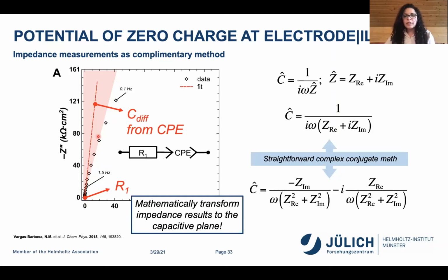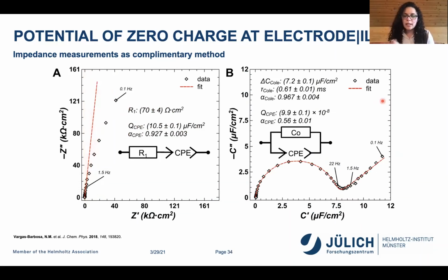And so what we did is we just mathematically transformed the impedance from the Nyquist impedance plane to the capacitive plane. We just did straightforward complex conjugate math. There's actually a program now that you can just click a button and it does it for you. And then you get such a plot on the right, where now capacitive processes, or processes that reflect a capacitance, look like semicircles. They're no longer hidden in this imaginary part that just shoots up to infinity. And so now you can, in a completely unbiased way, because this looks like a circle, we decided to use a Cole element, which is pretty much just the equation of a semicircle, to fit this.